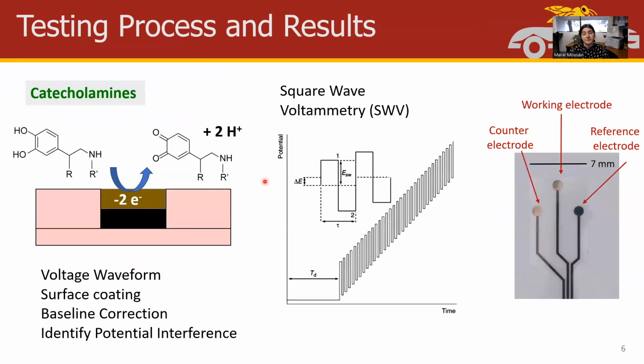We use a chemical reaction for generating signal. We have an electrode and we increase the potential at the surface of this electrode. As the potential increases, at some point, we have enough energy to steal electrons from these catecholamines, and that produces electrical current. Through measuring this electrical current at that specific potential, we can selectively detect these catecholamines and get information about their concentration. We use a specific waveform to maximize sensitivity and selectivity.